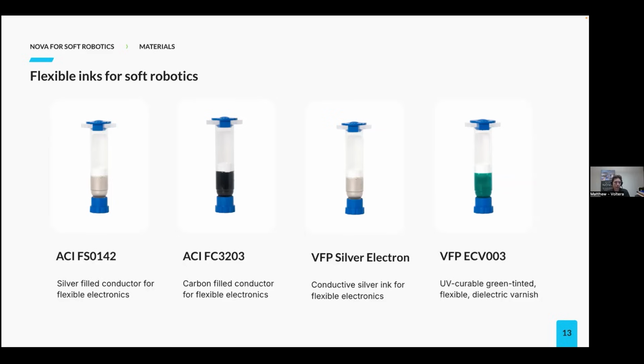Next is ACI's FC3203, and this is their flexible carbon conductor. It's a high conductivity carbon conductor and exhibits limited resistivity change when associated with bending and flexing. Carbon inks are great because they offer high thermal stability at a lower cost compared to silver. Their chemical inertness makes carbon suitable for printing resistors and conductors on non-conductive materials like plastics, ceramics, and paper. And they're often layered between silver inks to protect them from silver migration. They offer similar benefits as silver in terms of adhesion, ease of printability, and substrate compatibility.